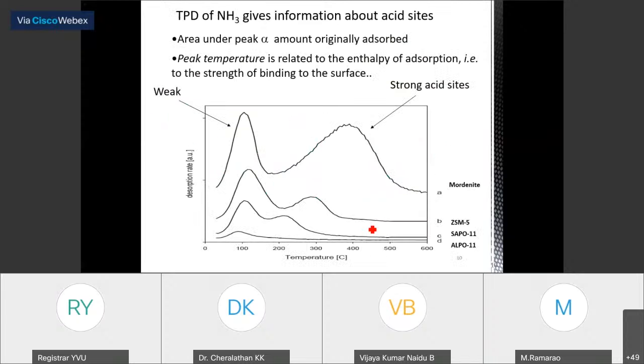So when you talk about acidity, how do you characterize these acid sites? Because in the case of liquid acids like sulfuric acid or hydrochloric acid, in the lab we can titrate and find out their strength. But in the case of solids like this, how do we study the acid sites? How do we find out the acid strength? There are some techniques. Temperature programmed desorption of ammonia is the widely used technique to know the acid sites and acid strength of the zeolites. Based on the temperature at which the adsorbed ammonia is desorbed, we can tell whether it has a weak acid site or a strong acid site.